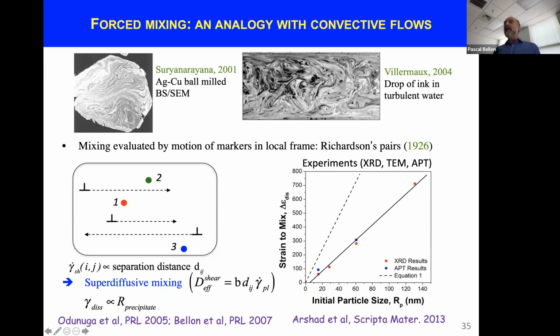So it is linear, but the slope is maybe 60% or 70% of the expected slope. But it is the right functional dependence. So I think you can say maybe there's an effective coefficient, or not all dislocations contribute equally. But it seems one case where this kind of mixing law was tested by experiments. I see. Thank you.